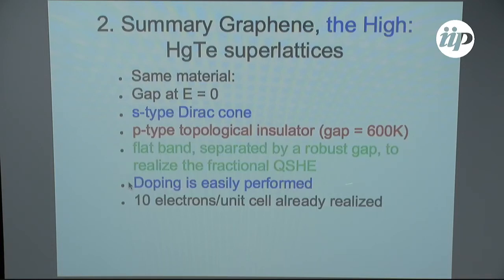And what is very nice is that I can go from one phase to the other by doping my system. They have not yet doped the full crystal, but by doping the individual nanocrystals, they have already achieved up to 10 electrons per unit cell. So you could easily dope and access all these higher bands, with electrolyte doping or gate doping. So it's a quite nice material, and they are trying to build that now at the moment.